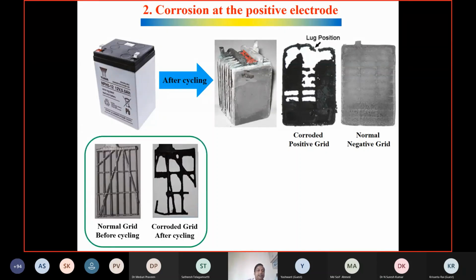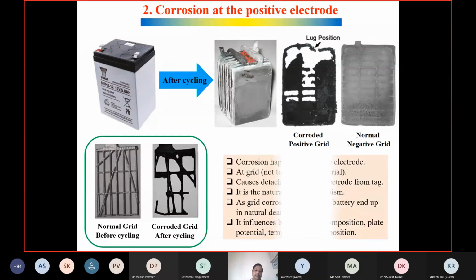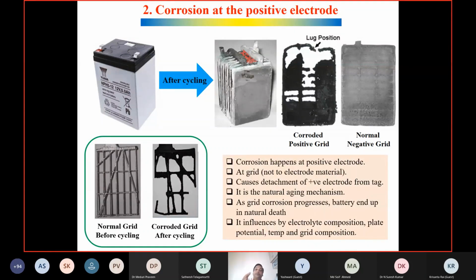So people try to see like this. This is our own electrode. This is the small electrode that a student prepared, and you see the configuration. Very strange. After 500 cycles, it becomes like this, completely corroded. So the active material is not utilized and it doesn't work. Okay, so the grid corrosion must be protected.